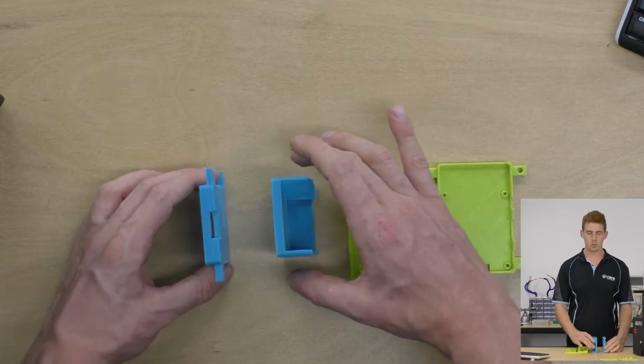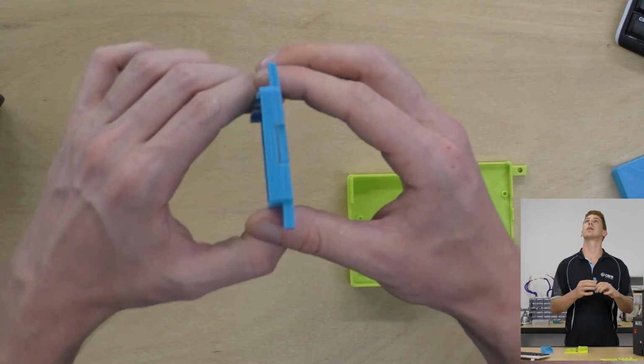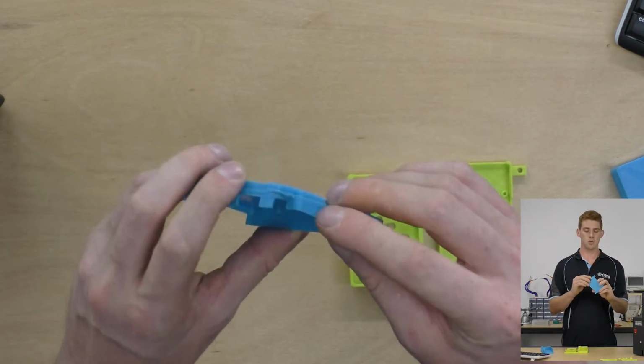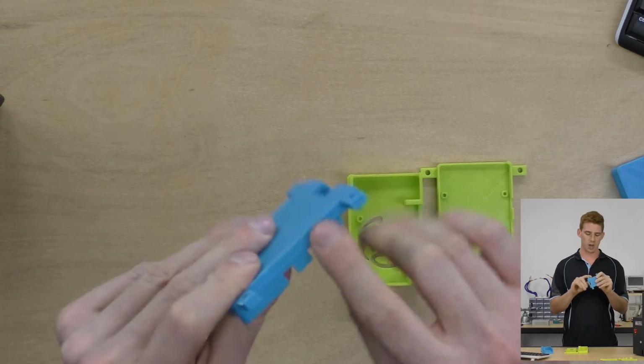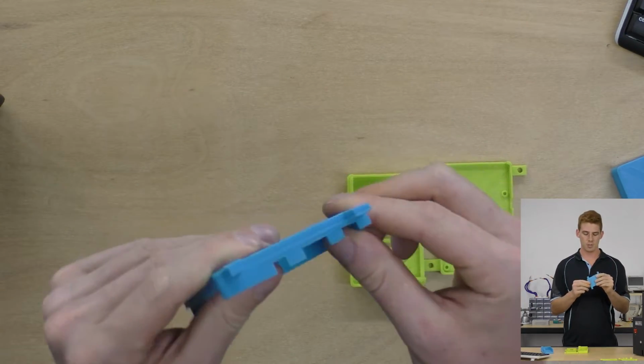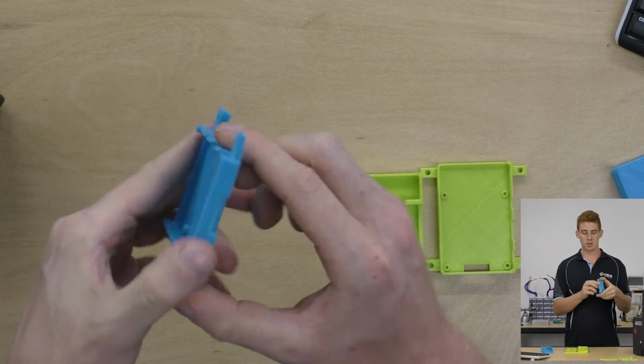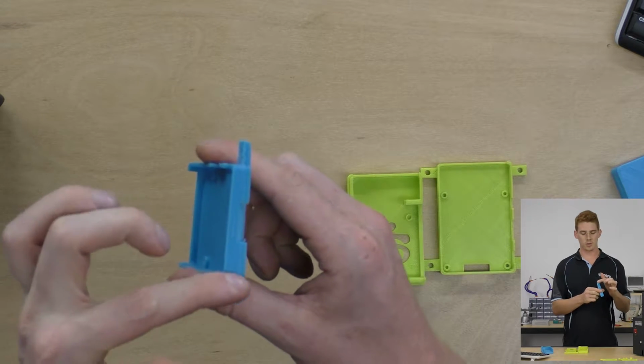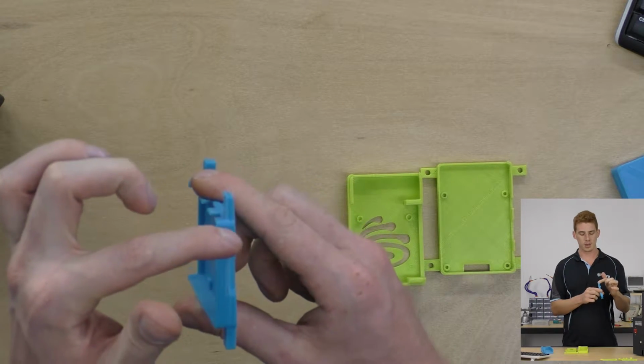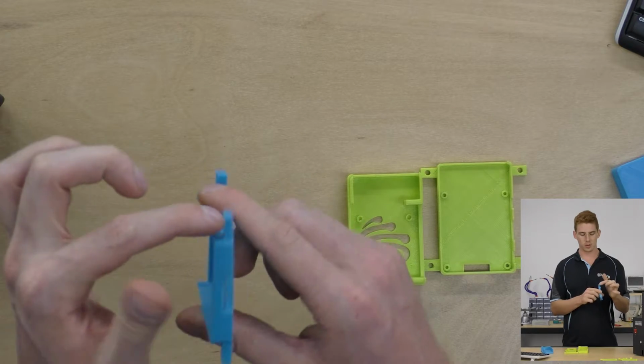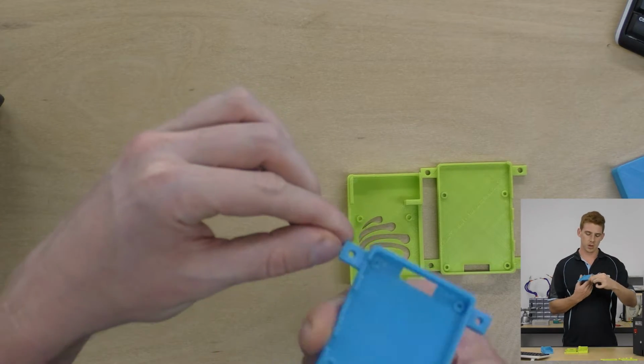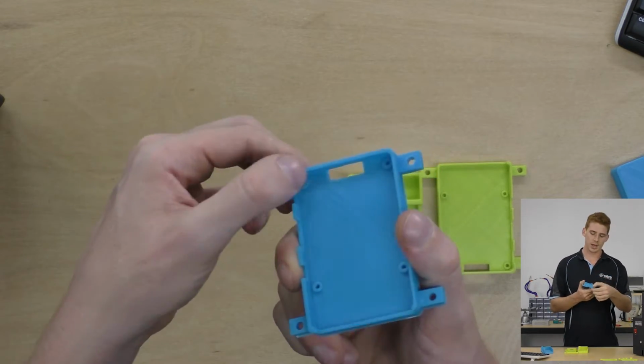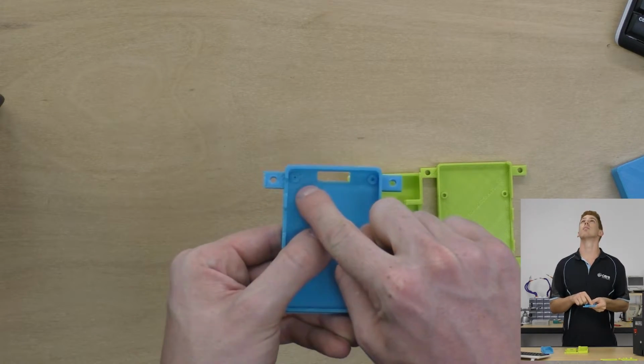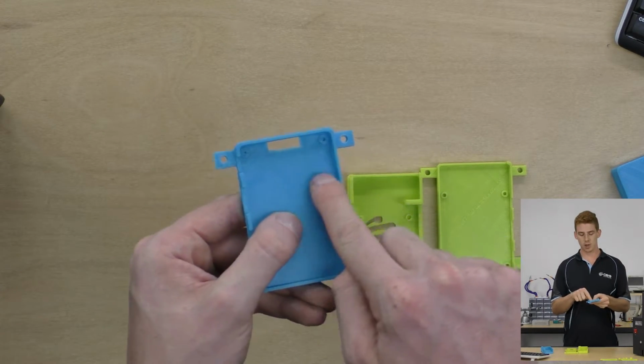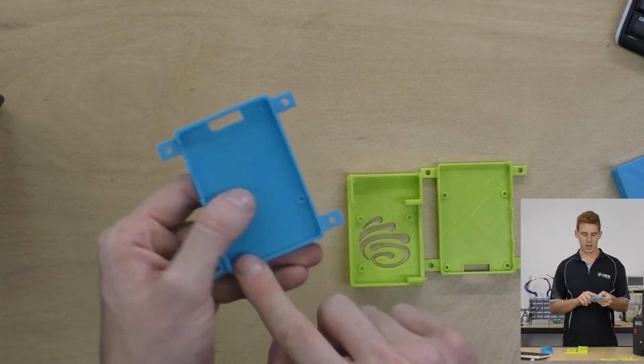So let's have a look at this one. Stand this one up straight. Now you can probably see all these artifacts on the edge of my print, and you might even think that's just like a bubbling print. What's actually happening is this print started warping up, and as it was warping up, the tool head was traveling over the print and it wasn't extruding in a flat uniform layer, but more like this bubbled, really terrible looking layer here. And you can see that it happened the most in this corner here. There was a little bit over in this corner, and these two corners were actually fine.